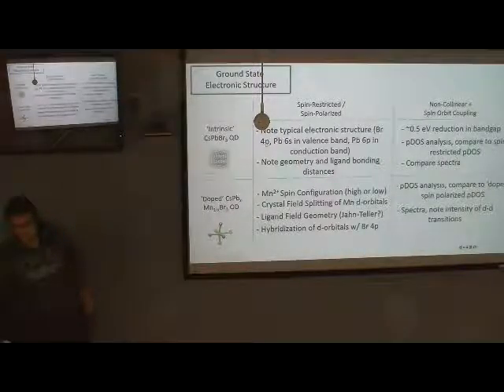It's either 4p or 5p orbitals, but they're p orbitals, and then lead 6s orbitals. And then in the conduction band, the band edge is made up of 6p orbitals. You can see that when you do partial density of states, or PDOS. So that follows what you'd expect for the system.